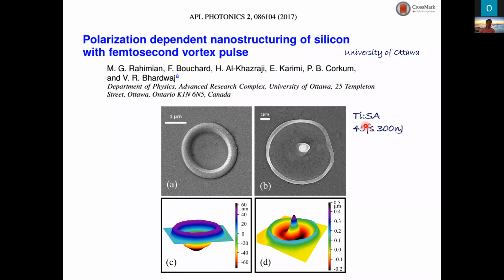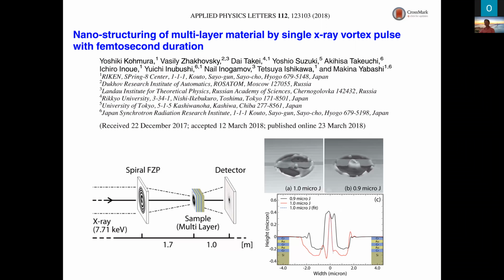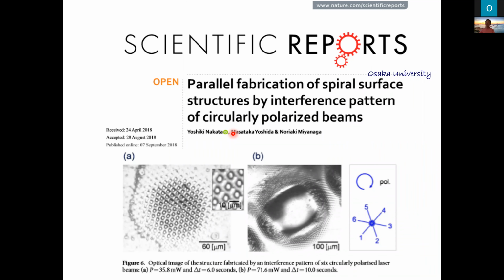Another interesting demonstration was performed by a Japanese group. They use a single X-ray vortex pulse with femtosecond pulse duration. They can also create a twisted needle on the substrate of multilayered semiconducting material. And this is also a Japanese group, Osaka University. They utilize a spatial light modulator and create a two-dimensional array of spiral surface structures by an optical vortex array. Such a demonstration is quite interesting. I like them very much. But I want to say such demonstrations must be just followers of our research. The first demonstration was performed by ourselves.